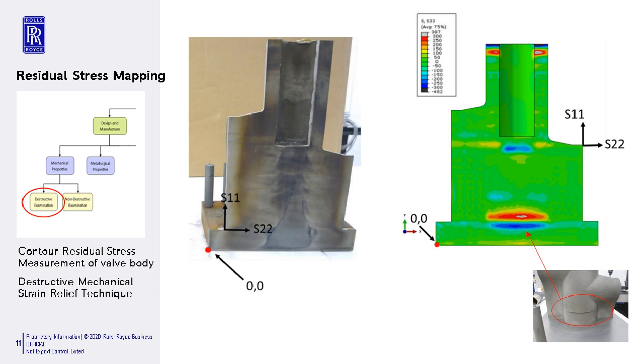We also, as you can see in the figure on the right, purposely introduced a defect in order to understand the residual stress effects from a lack of bond on the external surface of the component. And we also saw a surface effect on the upper section, believed to be due to the sectioning and measurement method applied.